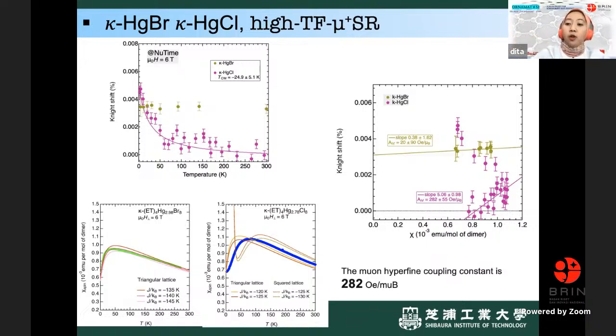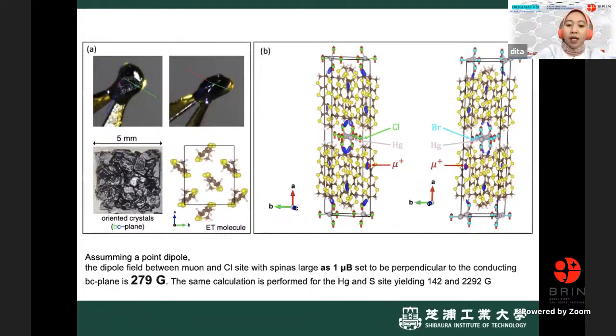of the chlorine. But then we can also estimate the muon hyperfine coupling constant to be 282 from the slope. Okay, 282 Oe per muB. And then, assuming dipole field calculations, I assume there is magnetism at the site. So this is the muon site from our DFT calculations. And we estimate that for the chlorine, between the chlorine site and the muon site, the hyperfine dipole field is around 279 Gauss. So we think that this is comparable with the Knight shift.